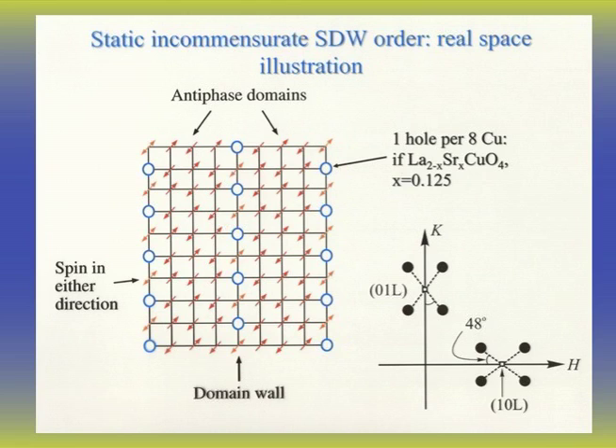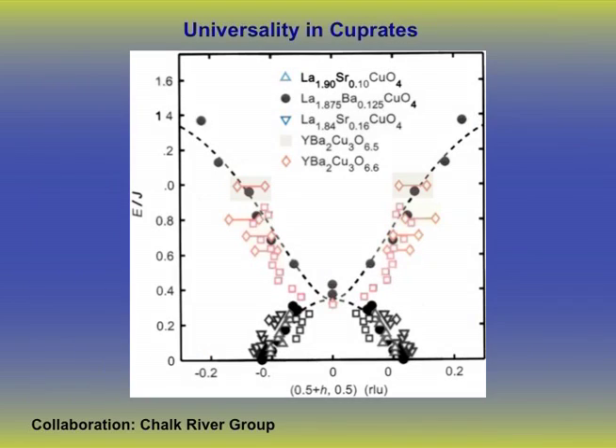My favorite model is one in which the charge carriers organize themselves into chains, basically, with the charge carriers going along these sort of rivers of charge and with the magnetic regions in between them. It's believed by many people that magnetic excitations mediate the superconductivity, by many, but by no means all. For solid-state physicists, this is what the dispersion relation looks like, which is that at very low energies, you have fluctuations which look like the stripes, charge stripes, moving against each other. There's a crossover point, and at high energies, you recover the excitations of the insulator.